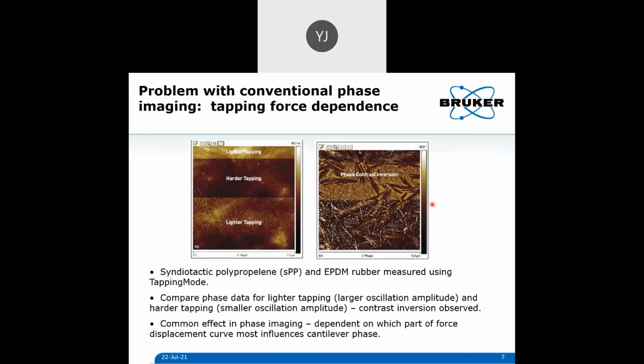We did mention that the phase contrast gives you some mechanical data, but it's very unreliable. If I change the amplitude of my oscillation, going from lighter tapping to harder tapping, you can see my phase contrast invert, right? So it's very difficult to say which is the harder material or which is the softer material. It depends on what kind of tapping you are doing. It can give you some contrast, but it doesn't tell you much more than that.